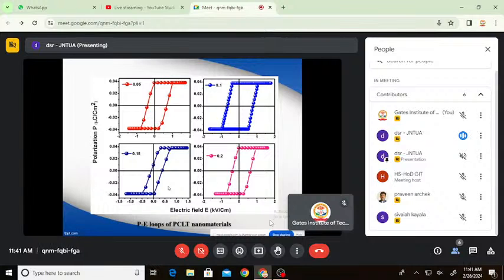But interestingly, in some cases, a small value of polarization is exhibited, which may be due to current leakage and the formed oxygen vacancies. Similarly, the remnant polarization was noted to be 0.039 microcoulomb per centimeter square for all the samples, except the y equal to 0.15 content. Hence, the samples may be desirable for ferroelectric capacitors and memory capacitors.